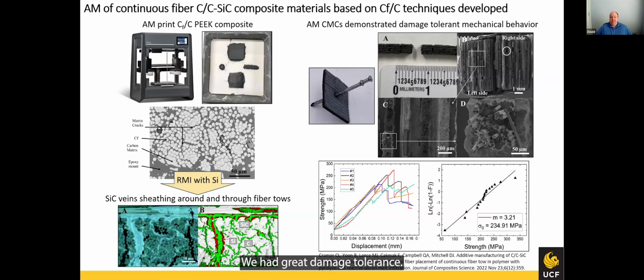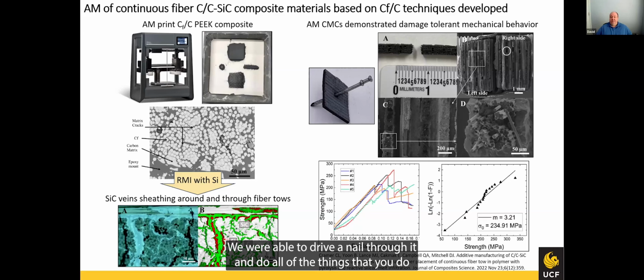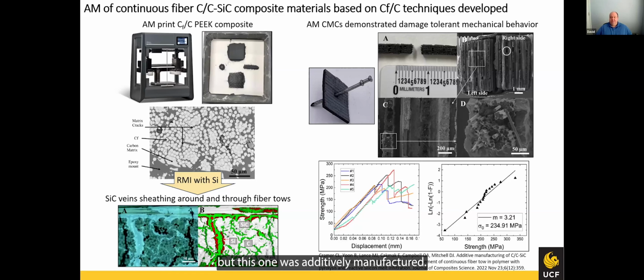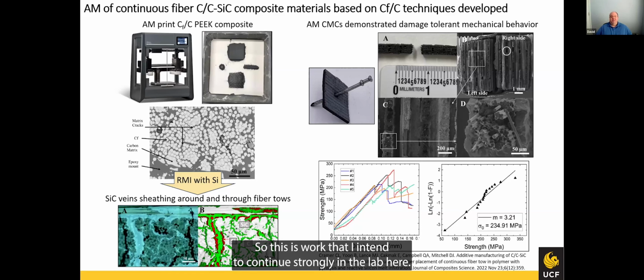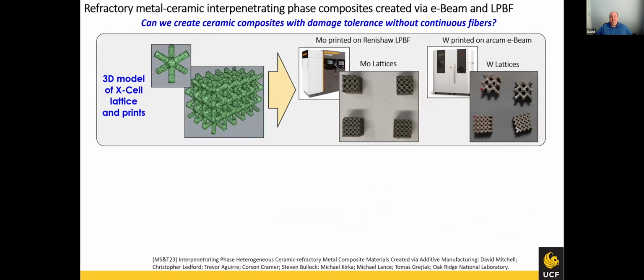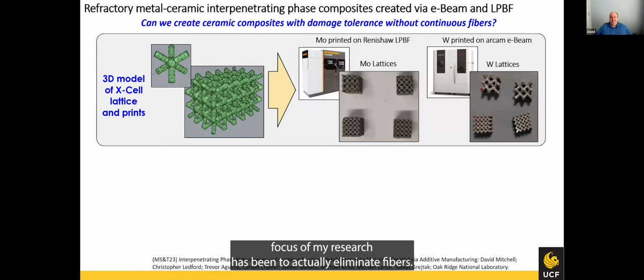We had great damage tolerance. We were able to drive a nail through it and do all of the things that you do when you try to demonstrate that a ceramic has damage tolerance, but this one was additively manufactured. So this is work that I intend to continue strongly in the lab here. The other real focus of my research has been to actually eliminate fibers. Fibers are very difficult to additively manufacture. They make life challenging, although they give you fantastic properties.